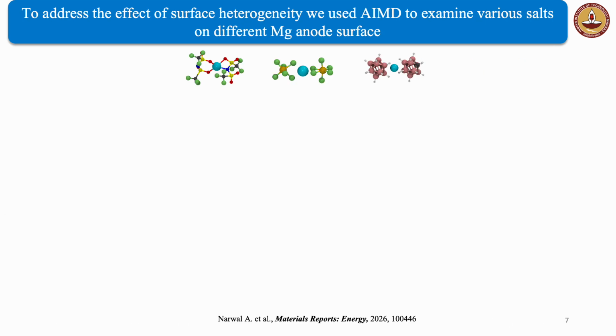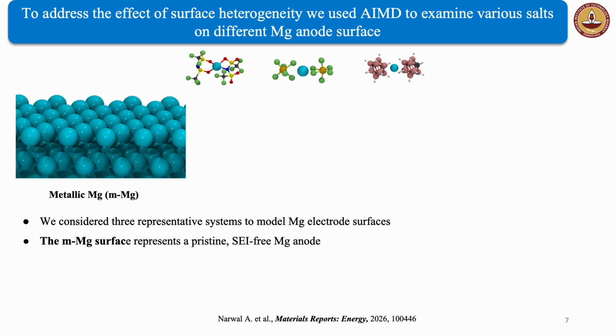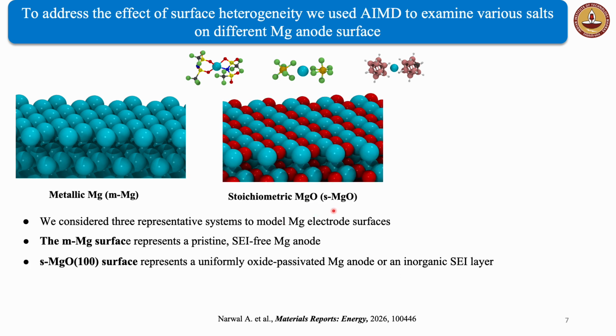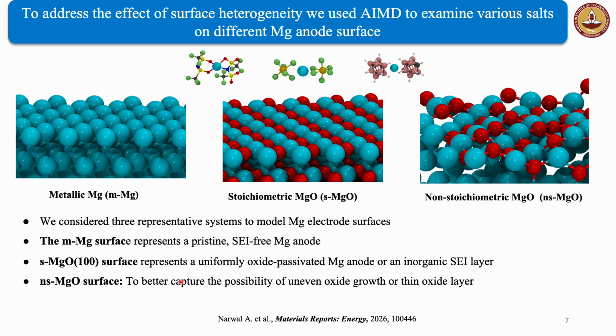So in this work, to address the effect of surface heterogeneity, we use molecular dynamics to examine the stability of different salts on various Mg anode surfaces. Basically, we considered three representative systems to model magnesium electrode surfaces. First is metallic Mg, which represents a pristine SEI-free Mg anode. Second is stoichiometric MgO, s-MgO, which represents a uniformly oxide-passivated Mg anode or an inorganic SEI layer. Now, experimental studies have suggested that the early-stage oxide layers on metallic Mg are typically thin, structurally heterogeneous, and oxygen deficient, exhibiting a higher Mg to O ratio. Therefore, we constructed a non-stoichiometric MgO surface, ns-MgO, consisting of a thin oxide layer on top of a metallic Mg substrate.